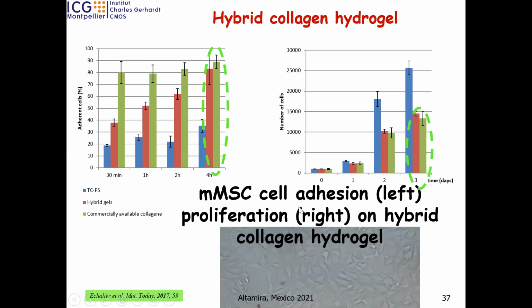Here on the left, you have the adhesion. You can see clearly the adhesion is very high. It's comparable to commercial collagen here, and our hydrogel is here. So it's quantitative. And what about proliferation of cells? You can see clearly it's similar to natural collagen, or commercial animal collagen.